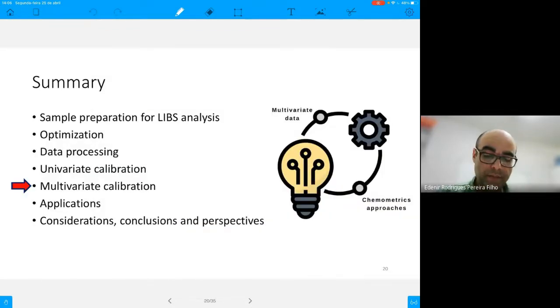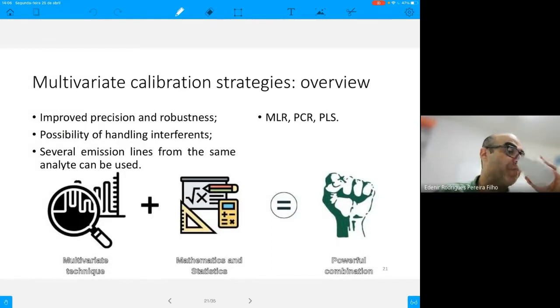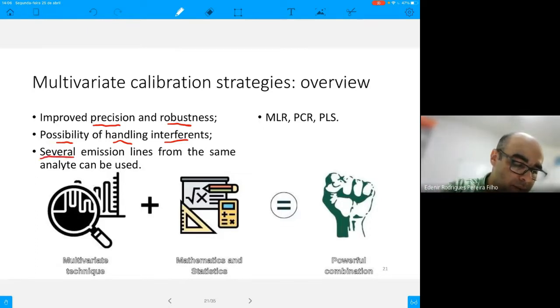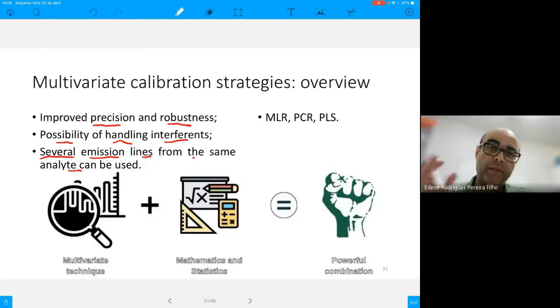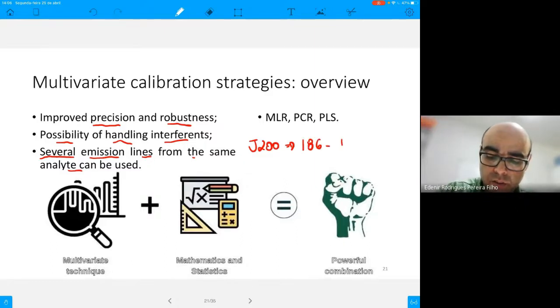Multivariate calibration. Multivariate calibration, we can improve the precision and the robustness of the methods. It's possible to handle interference if the interferences are in the calibration model. We can use several emission lines from the same analyte. As using LIBS, we can record several emission lines. For example, in the J200 instrument, we can record emission lines from 186 to 1042 nanometers, from the ultraviolet up to the infrared, passing through the visible.